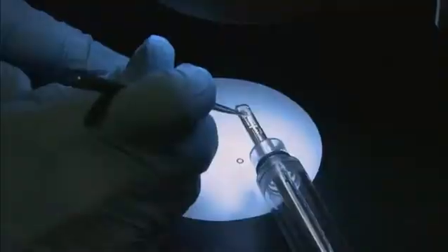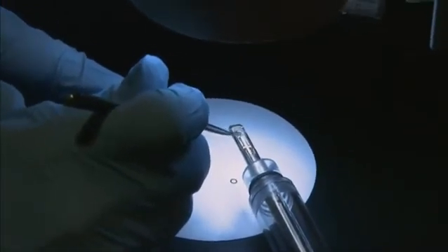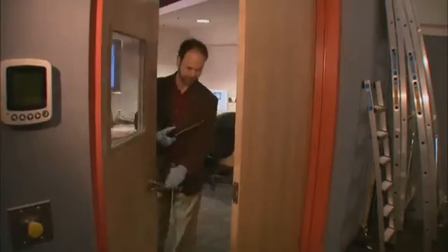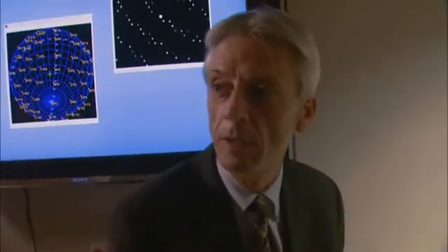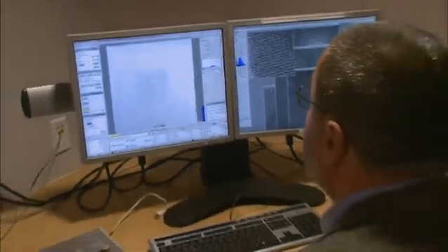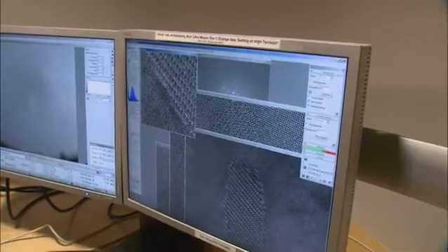It's very delicate. Figuring out the precipitate's precise atomic structure is essential in order to later test its strength. One of the most important things is to get the sample into the right orientation, so that you're looking down a row of atoms without any tilt — because if the row of atoms is slightly tilted, you wash out the resolution. The orientation looks good. Promising.